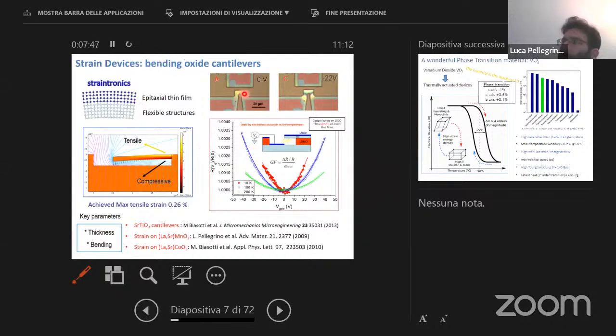So here is an example of a strontium titanate cantilever, as I showed you before. On top of this, we can deposit film by pulsed laser deposition. So we can place this structure in our pulsed laser deposition chamber and deposit all over on top the film, which grows epitaxially. And we have a good quality of the films. And this is an example of cobalt oxide films made by Michele Biasotti a long time ago, but shows that we can tune the strain. This is the resistance due to the increased strain in this structure as a function of the gate. So with the gate, we can bend the structure.